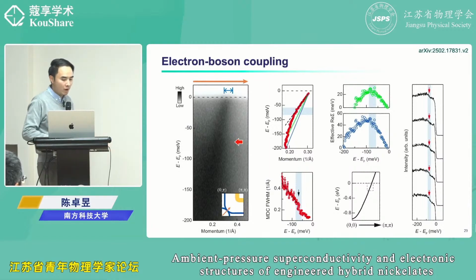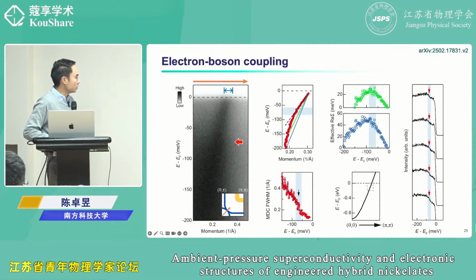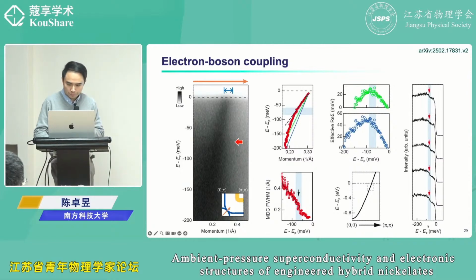The energy scale is about 70 milli eV. And from different analyses, you can see this kink in the MDC full width at half maximum, and also in the position of the kink. Also in the EDC, you can see the existence of this kink. So this bosonic mode is there, and may or may not be related to the pairing mechanism. That is also under discussion.